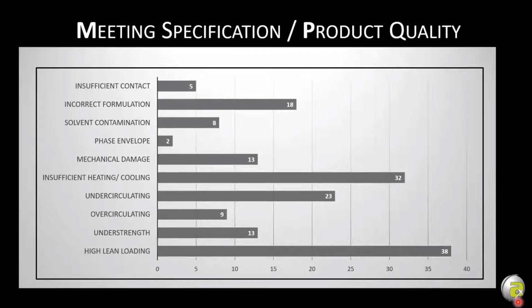The hugest one was high lean loading. Down here at 38 of all the opportunities, and 32 was insufficient heating cooling, which is basically the temperature. Here's the quality of the amine, the loading and the temperature. And also we've got contact. So mechanical damage and insufficient contact kind of go hand in hand. If the towers or trays are damaged, we don't get good contact. So these two are kind of hand in hand.